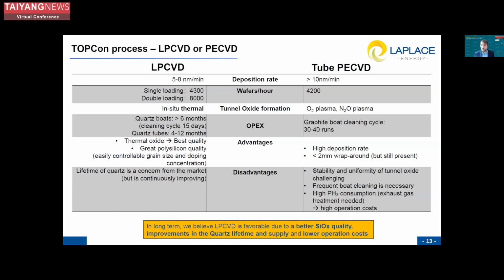So in the tube PECVD, we have the high deposition rate and a smaller wraparound, but from our understanding so far, since there is still a wraparound, it doesn't change much, as it's more about how controlled and how uniform the wraparound is rather than how much it is. And there the disadvantages are on the tunnel oxide, which is very challenging to reach good stability and uniformity, and also the high phosphine consumption, which needs then exhaust gas treatment, and this increases the operation costs.